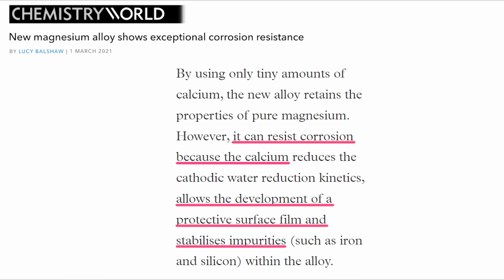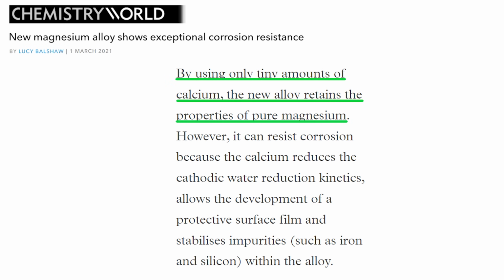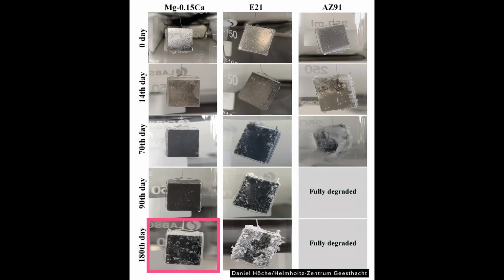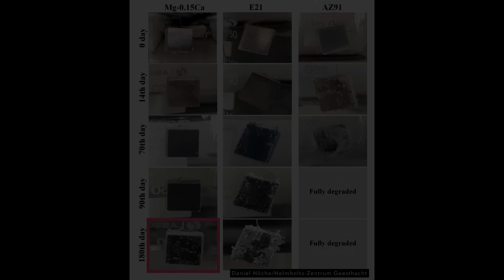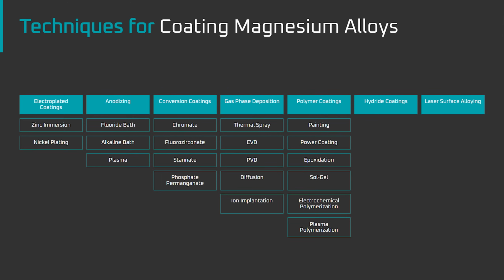The researchers claim that for the stainless magnesium, the calcium creates a protective surface film and stabilizes impurities within the alloy to reduce the corrosive effects of the sodium chloride solution. And because the calcium is used in such small amounts, it's able to do that while maintaining the properties of pure magnesium. That is, just like we saw with flammability, there's alloys available to mitigate the corrosion challenges with magnesium. It's also worth noting that besides corrosion-resistant alloys, magnesium parts can also be coated in a number of ways to further increase corrosion resistance. So if there is a use case that requires even better performance, there are solutions available.